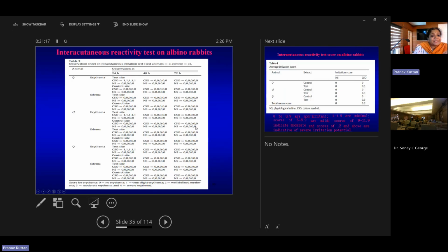This is the intracutaneous reactivity. As I explained earlier, the erythema and edema, that is the irritation found on the skin, is evaluated. That is, there is a scoring board that is used when saline was used, and when the cottonseed oil extract was used, and it will be tabulated for different time periods, that is 24 hours, 48 hours and 72 hours, and it was found that the irritation was 0.